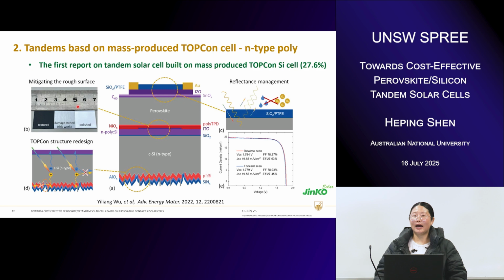At long distance, millimeter-level distance, the roughness could be up to micrometer level, from the highest to the lowest. So we had to cope with that challenge, because our perovskite is only hundreds of nanometers. So it is quite challenging to have a high performance perovskite on top of it. We coped with that challenge by developing a conformal nickel oxide layer together with some passivation layer on it. In the meantime, we optimized our perovskite fabrication process in a way that can give a good conformal layer on top of this rough surface. At that time, we were able to demonstrate 27.6% efficiency.